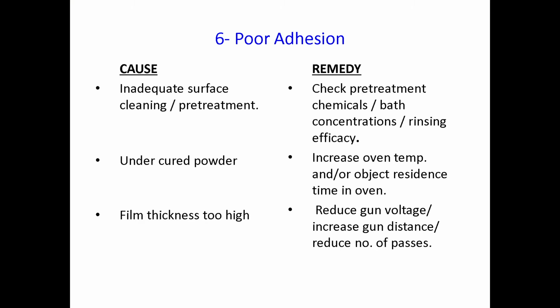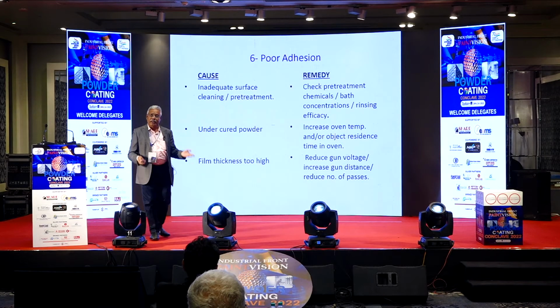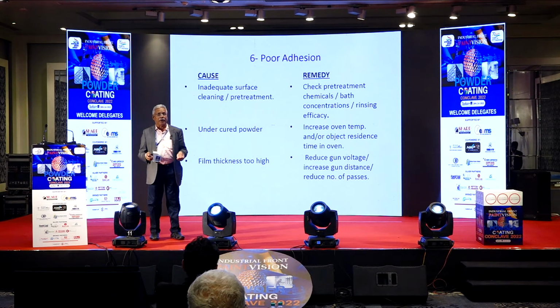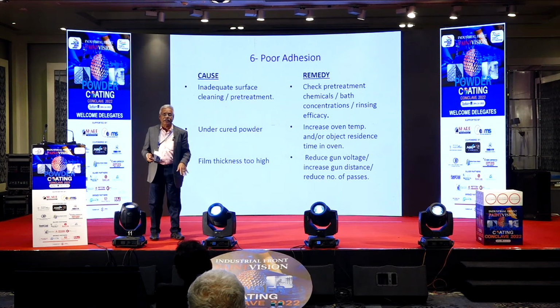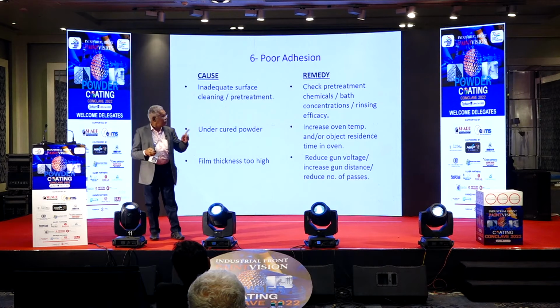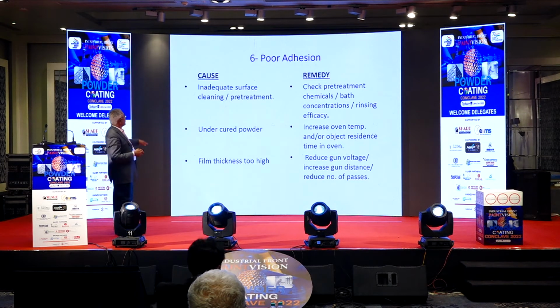Epoxy powder properties deteriorate due to storage at high temperature. Poor adhesion: inadequate surface treatment. Generally, 90% of our complaints come from poor adhesion because of the pre-treatment. Why? Because our coaters or customers do not go for proper pre-treatment. They do not do the 7-tank process. They will use a 3-in-1 solution or something, to reduce the cost of application. So the oil contents or residues will be retained after pre-treatment. In those cases, poor adhesion happens.